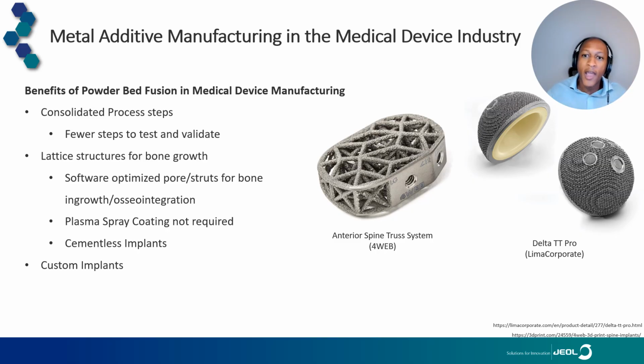By having a cementless implant and having a great surface between the bone and the implant, you can also avoid removing good bone that may be required to be removed in order to get good bone to implant contact. Lastly, another good benefit of additive manufacturing is custom implants, which would be a little more difficult for traditional manufacturing due to the lead times required to make a custom implant. With additive manufacturing, you're able to take a CT scan, do some initial designs, and create your near net shape custom implant that is specifically tailored to an individual, much faster overall than a traditionally manufactured implant could, and that helps potential patients who have a specific case for a custom implant.